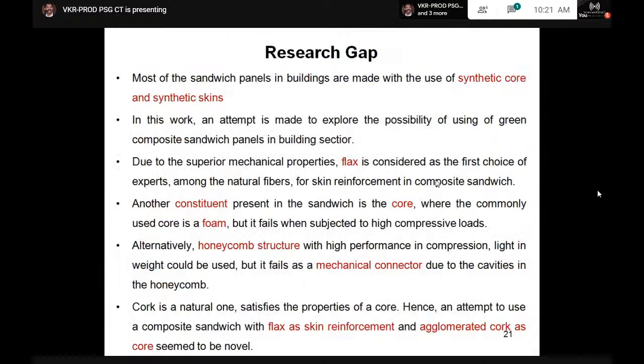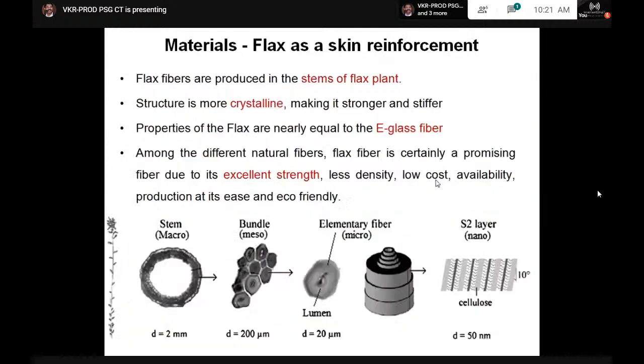So we took this as a research topic, and instead of going for a synthetic core and synthetic skin, we tried to use flax, a natural material, and instead of going for a honeycomb structure or foam, we used agglomerated cork as a core material. Of course, you can see the flax fibers are produced in the stems of the flax plant. The structure is more crystalline. It is an alternate to E-glass fiber, which gives excellent strength.